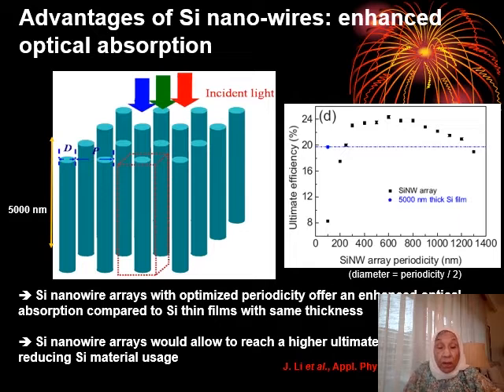So we can conclude from this that silicon nanowire arrays with optimized periodicity offer an enhancement of absorption compared to silicon thin films with the same thickness. Silicon nanowire arrays would allow us to reach higher ultimate values, reducing silicon material use. So putting that in mind, we started to think about our work. We started to think about preparing silicon nanowires.